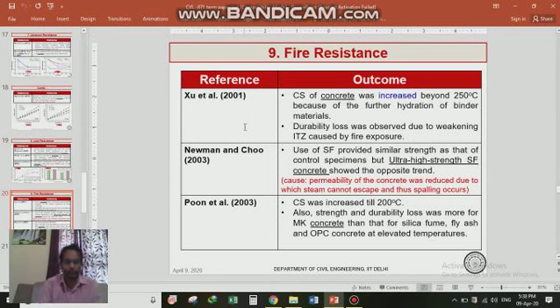The second conclusion was that durability loss was observed due to weakening of the ITZ caused by fire exposure. In 2003, Newman and Choo used silica fume, and they concluded that fire resistance was less for ultra high strength silica fume concrete than for the controlled sample, because silica fume is very fine and decreases the permeability of concrete too much, due to which steam pressure, vapor pressure can't escape. Therefore, spalling occurs for ultra high strength silica fume concrete.